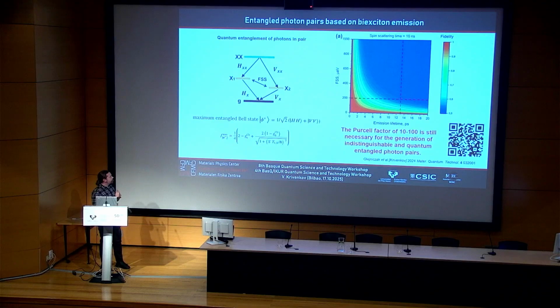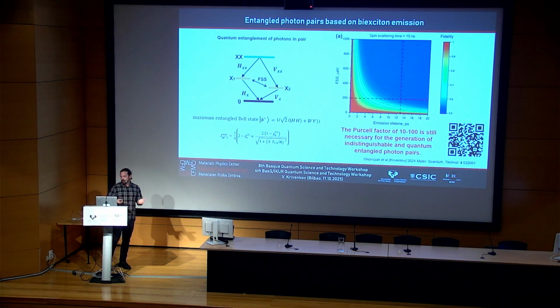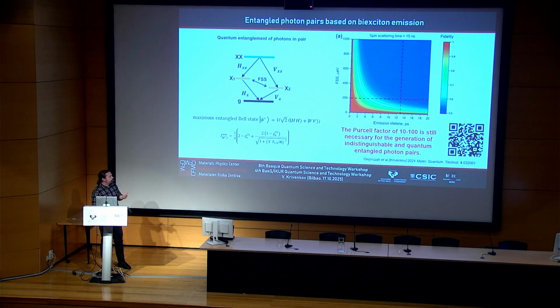However, there is one problem with semiconductor quantum emitters in general: the presence of a crystal field leading to fine structure splitting, which ruins the entanglement of the photons produced from this cascade recombination, because different polarizations will have different intermediate exciton level energies. And if we look at how the quantum dot parameters relate to the entanglement fidelity, we will see that the lifetime of the intermediate exciton state is also very important. The shorter this lifetime, the less effect the fine structure splitting has on the system. So it's still quite far away, to be honest, from achieving any entanglement fidelity from colloidal quantum dots.